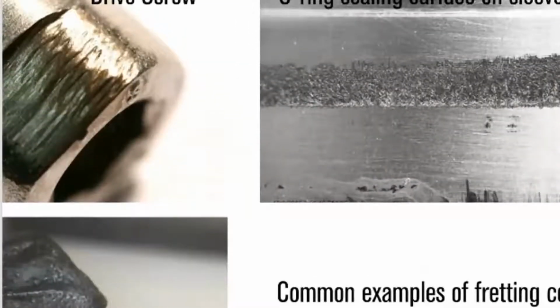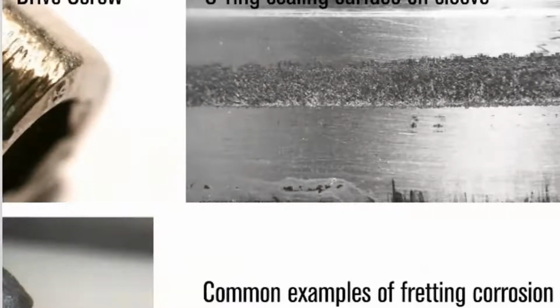Man, that's a good photograph, isn't it? Look how straight it is. And you can see it's fairly shallow here, and then it gets really deep into here. And that's because any oxygen that is swept under here never leaves. This oxygen might get pushed out again, but it never leaves. And you can see right about here is where it's really deep.